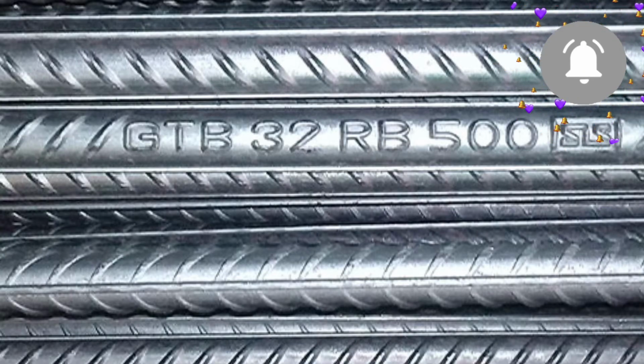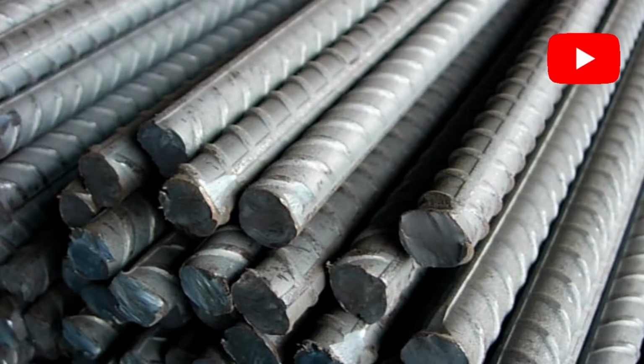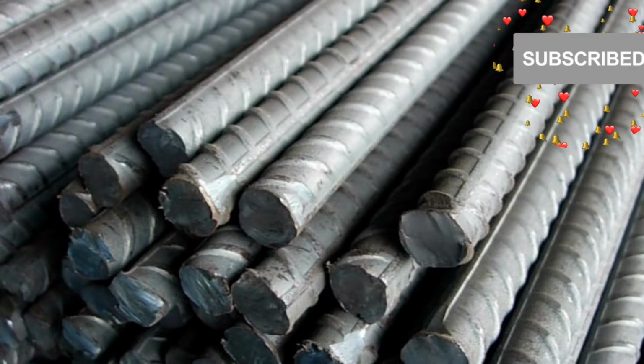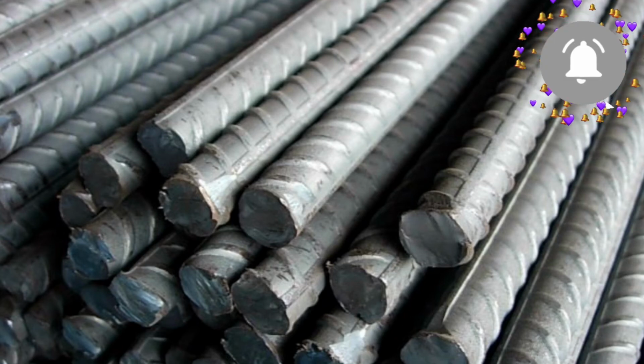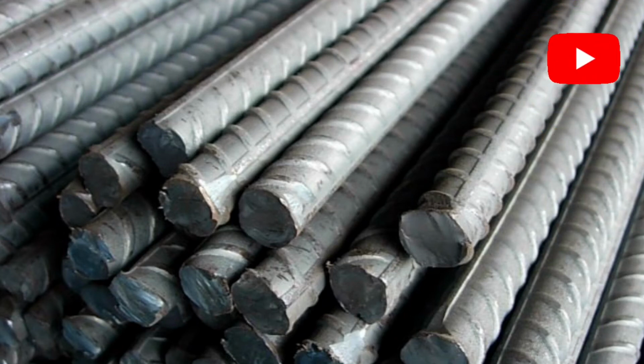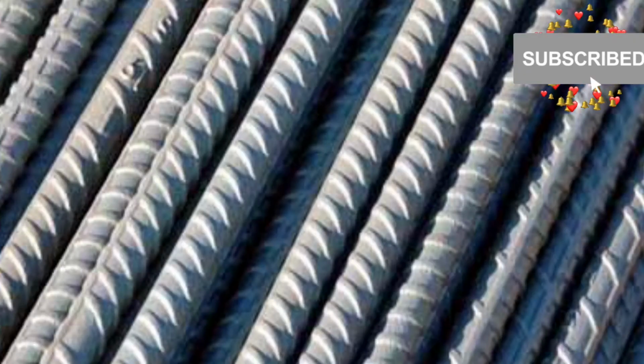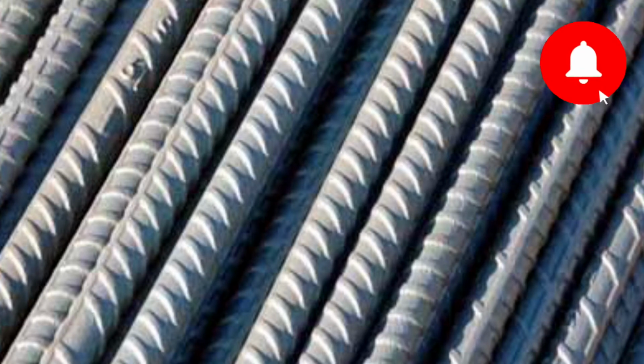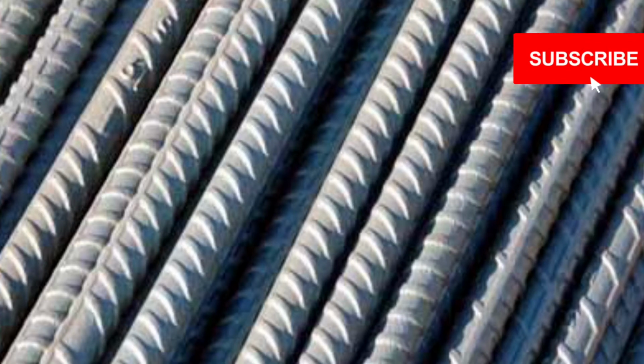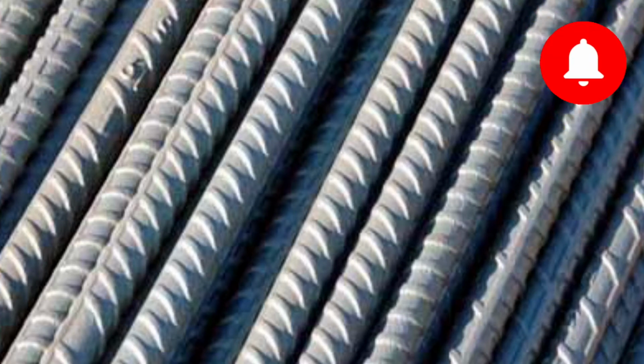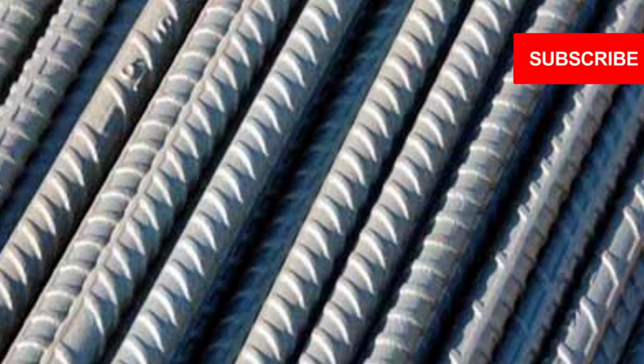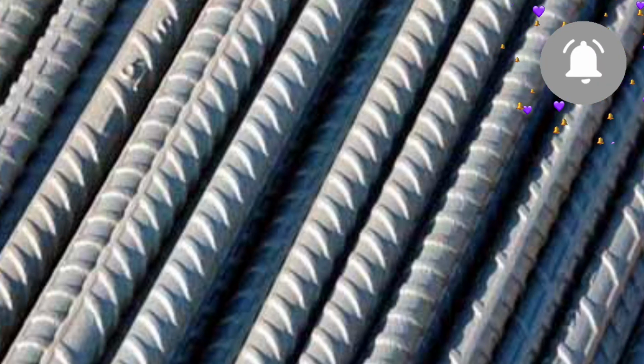There is a formula to find the weight: d squared over 162. For example, you have 10 mm of steel bar. So now we are going to check the weight. So the formula is d squared over 162. Here d is 10 mm, so here 10 squared over 162. So weight should be 0.617 kilogram or 617 gram. If not, just reject it.